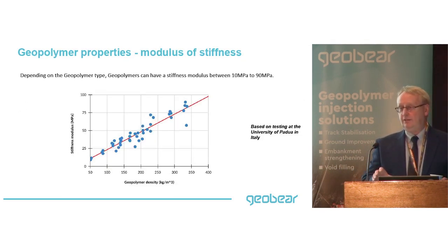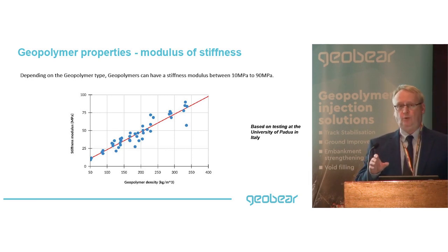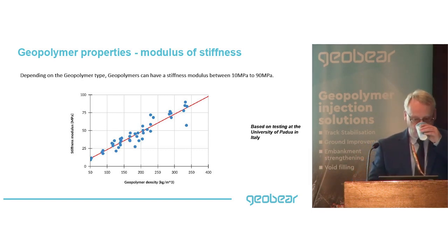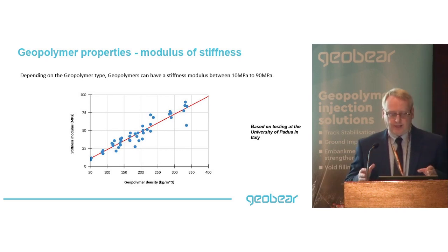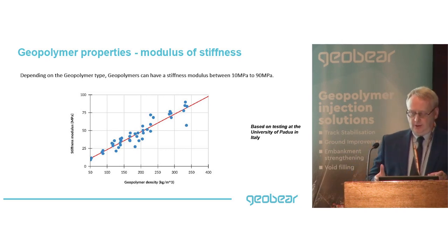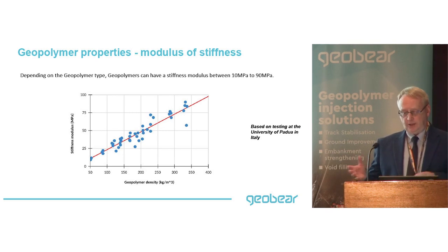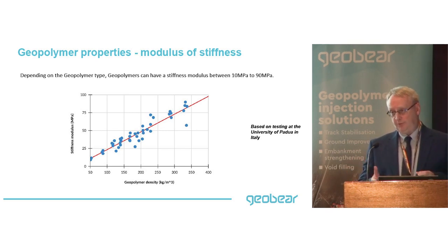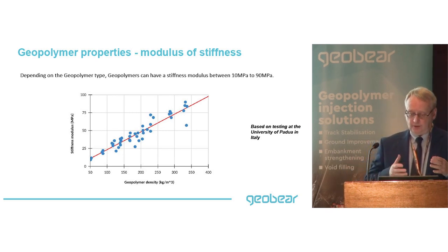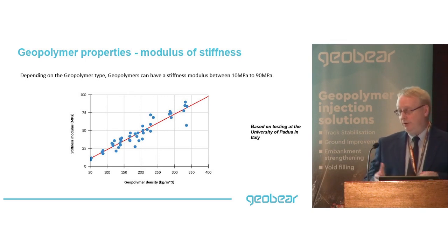And we test these material properties in the lab, so we know what the physical properties of the material are for any given density, and you can work out the relationship between density and strength. It's very important. You would expect the stiffness to go up as the density increases, so it's sort of proportional to the compressive strength - the stiffness modulus increases proportionate with the density.